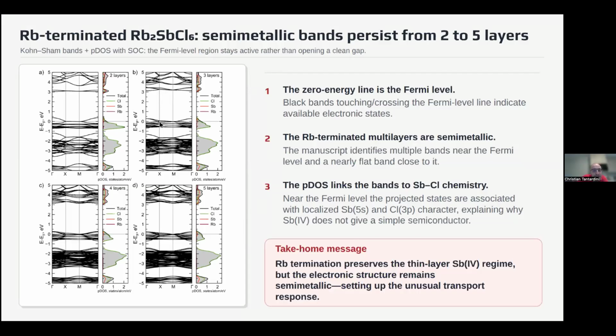What we have seen, as you see here, I don't have the pointer, but if you look at X and close to M, for panel A, which is the 2 layer, it seems that the conduction band and the valence band touch each other. At the beginning, we were thinking that we had found a Weyl semi-metal. But the analysis that we performed disconfirmed this. Actually, it's a kind of nodal line semi-metal, where the conduction band and valence band touch each other. The same but more complicated we have seen in the 3 layer, and the 4 and 5,